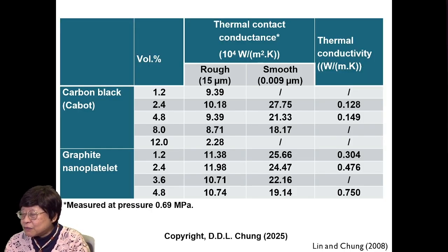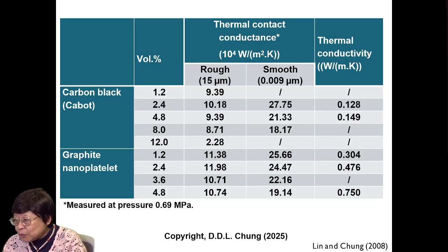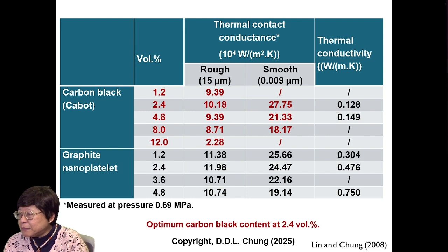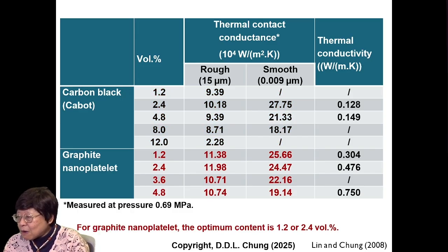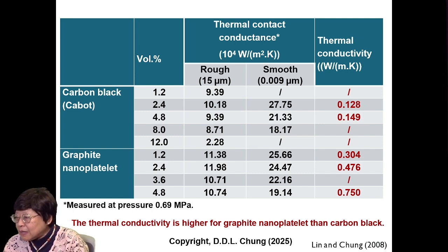Shown here is the comparison of carbon black and graphite nanoplatelet for different volume fractions, showing the thermal contact conductance for the rough and smooth copper surface case, and also the thermal conductivity. And you can see that for carbon black, the optimum carbon content is 2.4 volume percent. The 2.4 gives the highest value of the thermal contact conductance, whether for rough or smooth surfaces. For graphite nanoplatelet, on the other hand, the optimum content is either 1.2 or 2.4 volume percent. The thermal conductivity is higher for graphite nanoplatelet than carbon black.